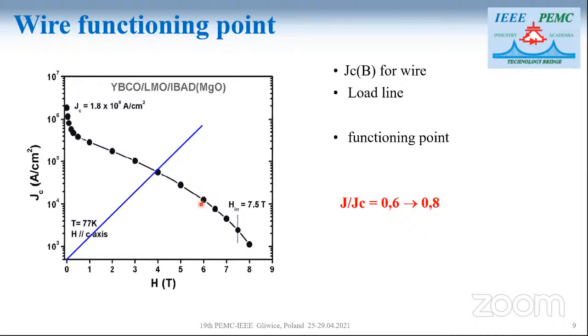Moreover, we take care to take a safety margin. So the current density is about 60 or 80% of the critical current density. This part is one of the key points when designing a superconducting winding. But in certain cases, you can increase this value and work really near the critical current.